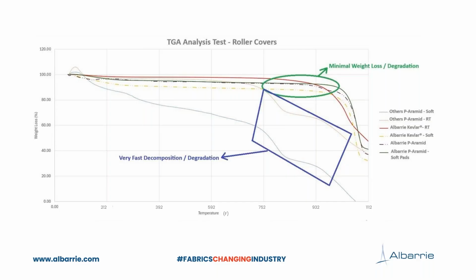This analysis revealed that the roller covers in question, which were labeled as 100% Kevlar or para-aramid, actually contained filler fibers to cut costs. These filler fibers significantly compromise the thermal stability of the materials, leading to rapid degradation at high temperatures.